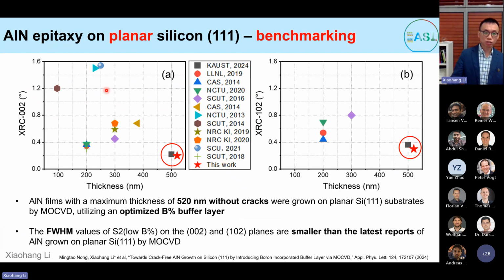So here are some benchmarking data. We compare our work with previous reports on planar silicon 111 samples. So far we have realized the largest thickness without cracks, as well as the lowest full width at half maximum for 002 and 102. Of course, we are still trying to improve it so that we can push the thickness higher, which will help us reduce the amount of dislocations in the film.